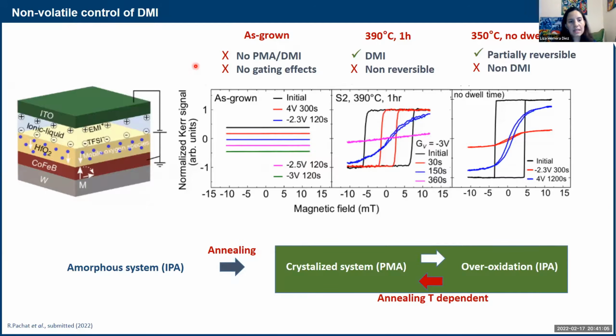It's known that in systems with a tungsten substrate, the structure of the tungsten cobalt iron boron interface is also very, very important for PMA. So we understood at this point that it doesn't matter how much oxygen we put inside, we will not see PMA. We really had to anneal and then have this nice crystalline interface between the cobalt iron boron and the tungsten. So this is what we did. We annealed it, and then we could see PMA, we could see DMI, but however, it was non-reversible.